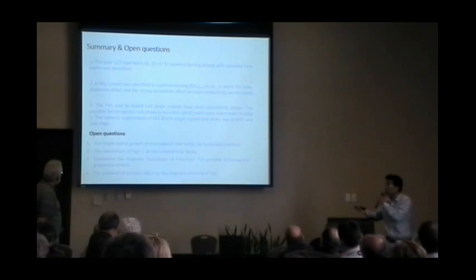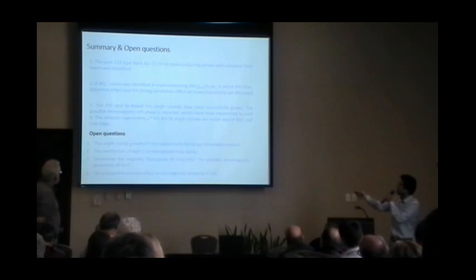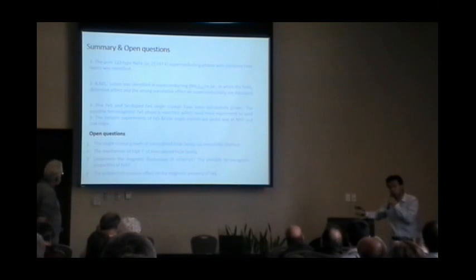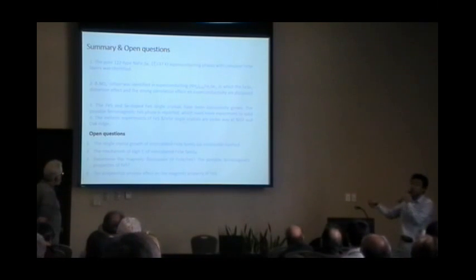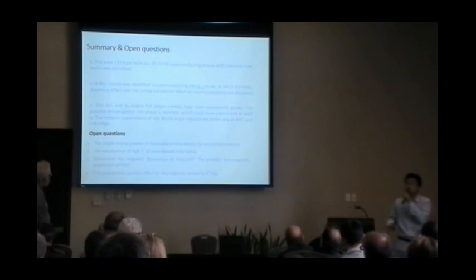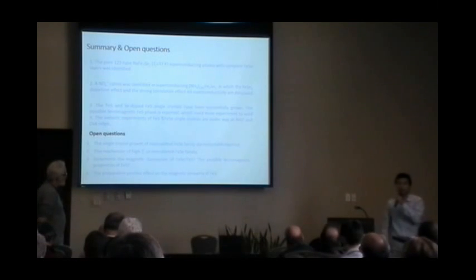But for the second one, now we have 2 PhD students. They are doing the inelastic experiments about the iron sulfur sample. The crystal structure of the iron sulfur is the same as the iron selenide. But this is a new single crystal we got. So we want to do some inelastic experiments to find out why there is TC when it's superconducting, and how the TC correlates with the spin fluctuation. We got this sample maybe 1 month ago.